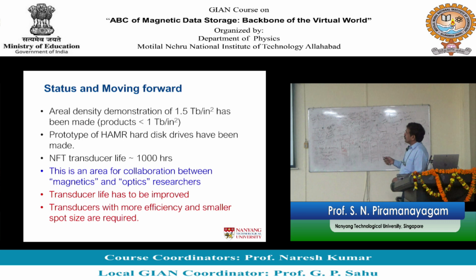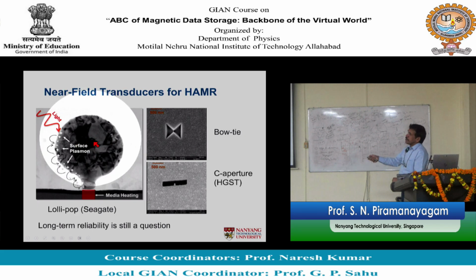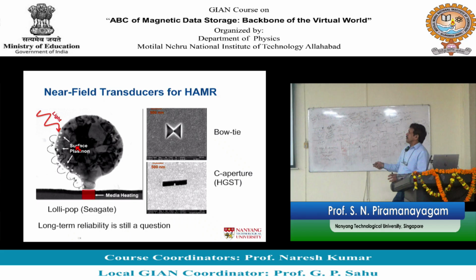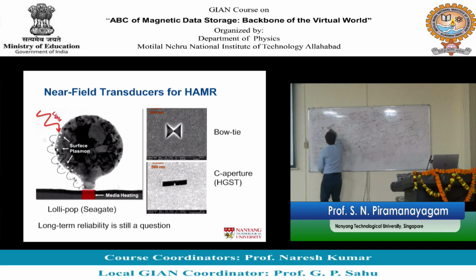Because of that now people can demonstrate HAMR, and one problem for a very long time has been the life of the transducer. Okay. You keep heating this surface plasmon. Let us say initially it is made of gold. Okay. This lollipop was initially made using gold, and let us say initially your grains in the gold were 20 nanometer in diameter. Okay, then you get some property.